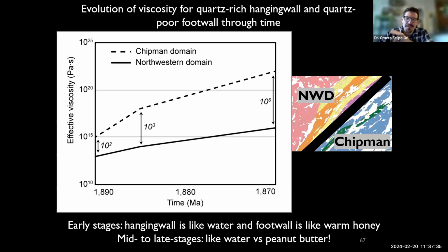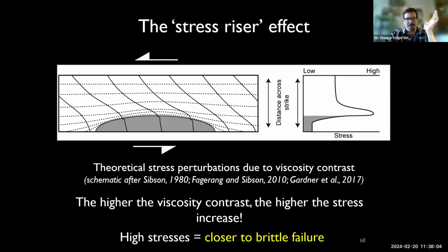But then as time kept going, right, and the temperature pulse from those mafic dikes waned and waned and waned, towards the later stages of this shear zone's history, the contrast between both halves of the shear zone became extreme, essentially, right? So by the mid to late stages of the shear zone's activity, the viscosity contrast was closer to water and peanut butter. And so that is not a happy ductile deforming situation.